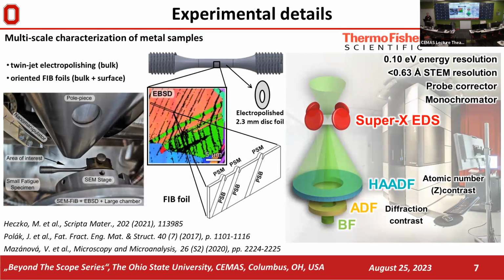So as I said, we are dealing with multi-scale characterization of metal samples. We are dealing with metallurgy, and in a lot of cases, we have a sample which is quite large. It's from a mechanical testing machine, and we have to go from this microscopic length scale to nanoscale. So how do we do that? Traditionally, we use jet electropolishing. We cut a piece of material, we polish it down to a few hundred micrometers, and then we electropolish, and we can use it in our state-of-the-art systems.